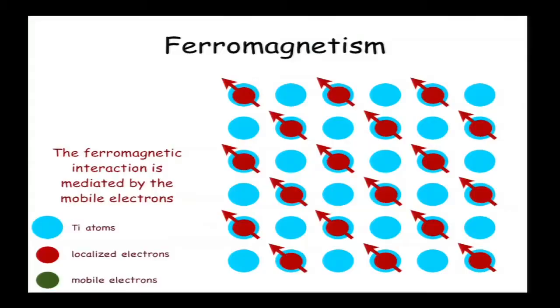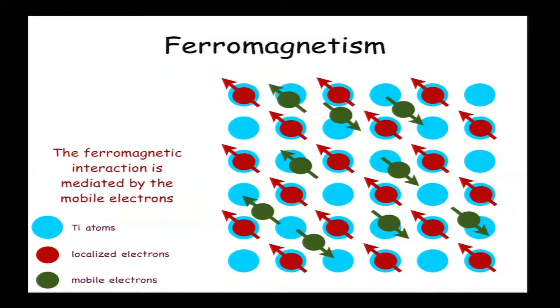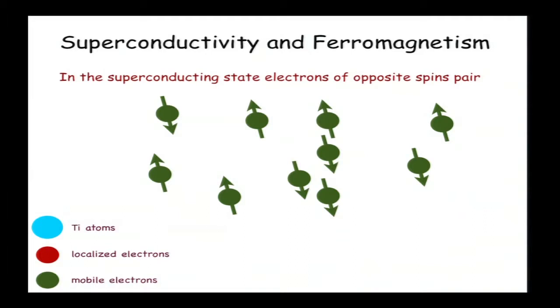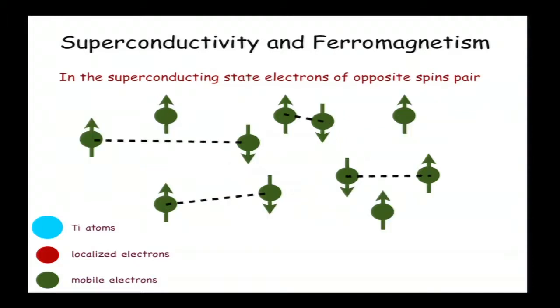Therefore, when our mobile electrons are moving along the sample, they are polarizing the localized electrons. And that's how we get our ferromagnet. All the spins are pointing in the same direction. Obviously, because all the localized spins are pointing in one direction, most of the mobile spins will point in the opposite direction, and we will have more mobile spins pointing in one direction than in the other. And that is not good for superconductivity. Superconductivity occurs when electrons of opposite spins form pairs, what is known as Cooper pairs. But we have more electrons of, let's say, up spin than down spin, so not all the electrons can actually pair. And these unpaired electrons are going to destroy the superconducting state. If there are too many of them, we are not going to see any superconductivity.